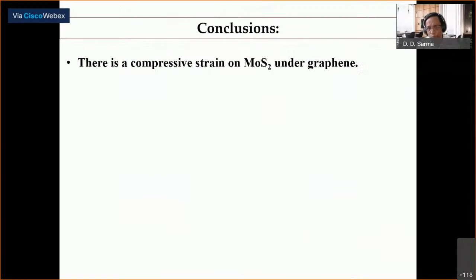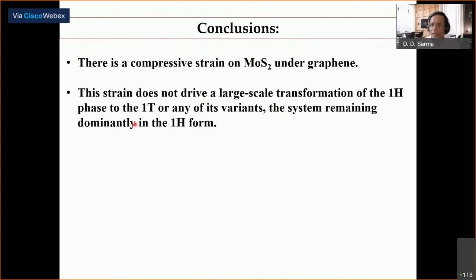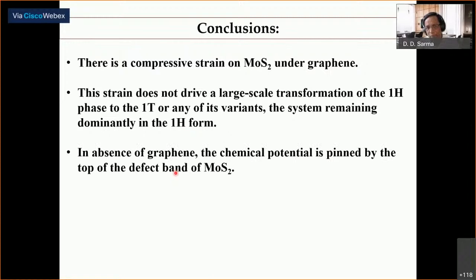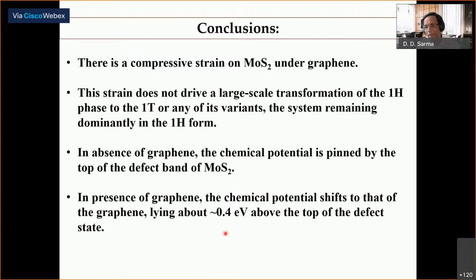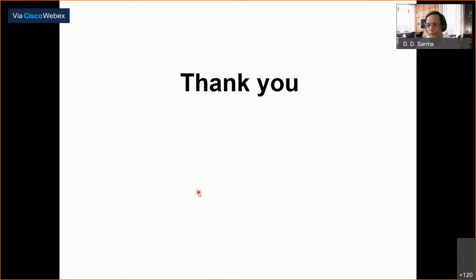All that is happening is the local Fermi energy is changing between the heterostructure and the part which is away from the heterostructure. What we conclude is that though there's a compressive strain on molybdenum disulfide on the graphene, there's no transformation of the H phase to the T phase or any of its variants, because we know what the T phase looks like from the detailed study that I didn't tell you about, but is already published. In absence of the graphene, away from the graphene, the chemical potential is really pinned by the defect bands of MoS2. There are always some defects, but when you bring in the graphene, now the chemical potential is pinned by the graphene, which lies about 0.4 electron volt above the top of the defect state, and that's why it shifts by 0.4 electron volt. And with that, let me end my talk, thanking you for your patience.